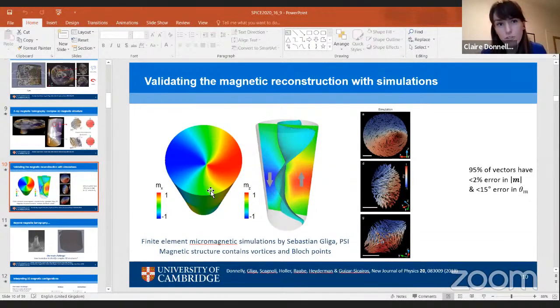Now, the major limitation of XMCD 3D imaging is that we struggle with highly divergent structures, in that we cannot reconstruct purely divergent configurations. The way we can understand that is, if we have a hedgehog structure, we have compensating spins from all directions. The total XMCD contrast of that is always going to be zero, whether they are pointing in or pointing out. For these length scales, we're relatively lucky, because this limitation translates to a slight lowering of the magnitude of the magnetization in the vicinity of these divergent structures. But we're still able to reconstruct the direction very accurately. That is something we're now thinking about, alternative types of measurement that could get around that.